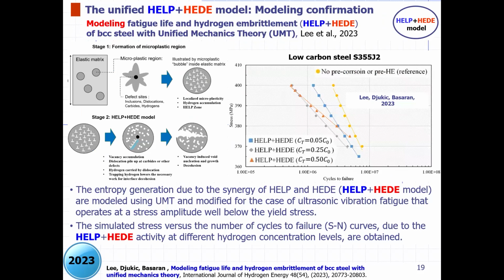One slide more in order to confirm those mechanisms. Together with Professor Basaran from the University at Buffalo and colleagues from China, we provide a very comprehensive paper, published in 2023, in which we tried using unified mechanics theory, which is an entropy-based ab initio method, to confirm the validity of the HELP HEDE model on the physics level, on a fundamental level. And we have some very promising results. We implemented the HELP HEDE model and the transition between mechanisms in the case of high cycle fatigue of pre-hydrogenated material, and confirmed that due to HELP HEDE activity, we have a shortening of fatigue life, as you can see here on the diagram.